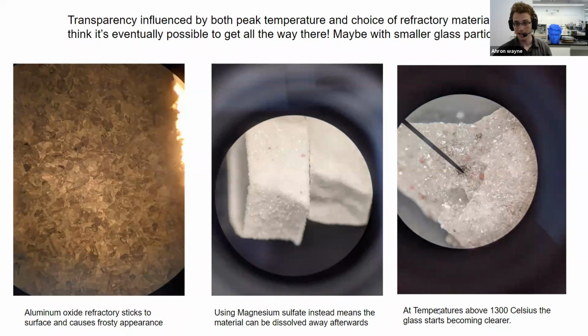And then we can see that as the temperatures increase, especially above 1300 Celsius, I've tried between 700 and 1300 Celsius, the glass starts to become transparent. And I think it's possible to get all the way there, maybe if we use smaller glass particles next time.